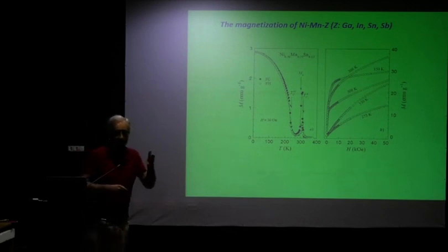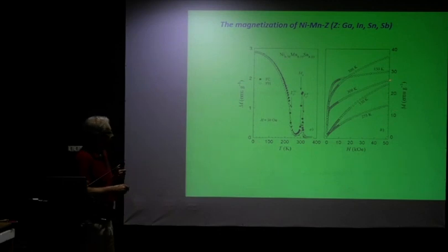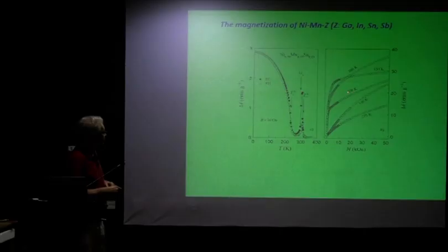That is, the high field susceptibility is the slope here. The higher the slope, the higher the high field susceptibility. And that tells us that we have non-ferromagnetic components of some sort in there that give rise to this. So that's at 300 Kelvin. I forgot about 306 Kelvin, of course.